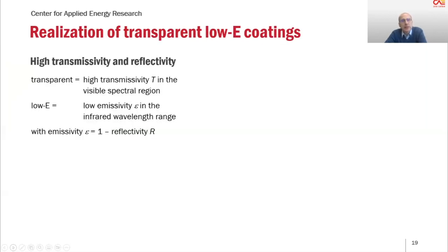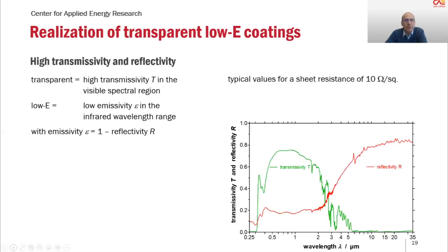So on the next slide, you see the values for typical low E coatings based on silver nanowires. So as already mentioned, we want to have a high transmissivity in the visible spectral region and a low emissivity in the infrared spectral region. And low emissivity in the infrared spectral region means high reflectivity in the infrared spectral region. So here you see the graph. The transmissivity in green and the reflectivity in red is printed over the wavelengths.